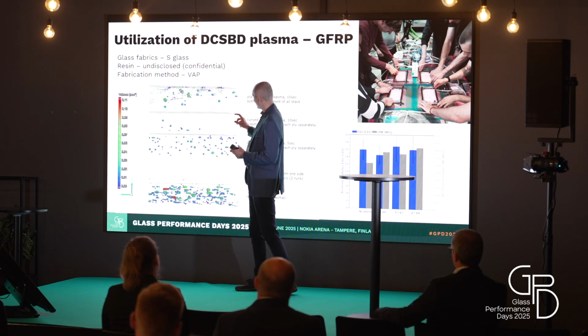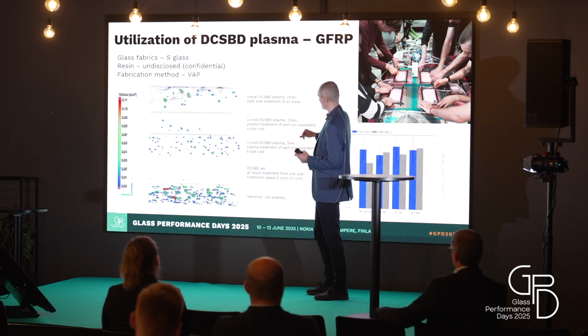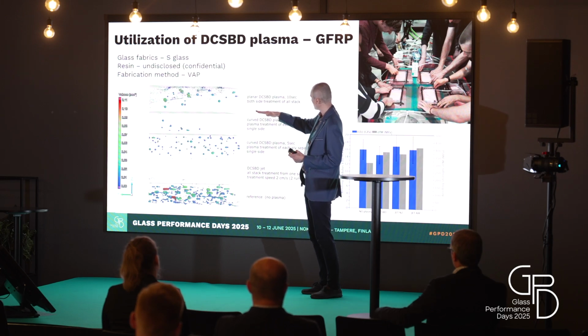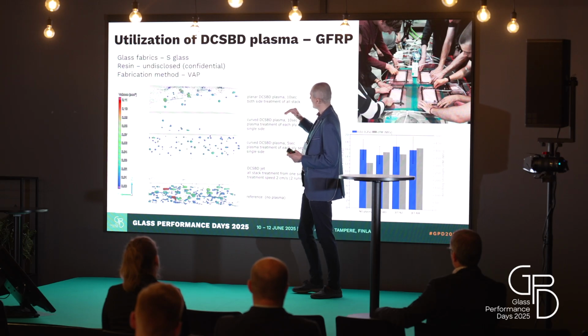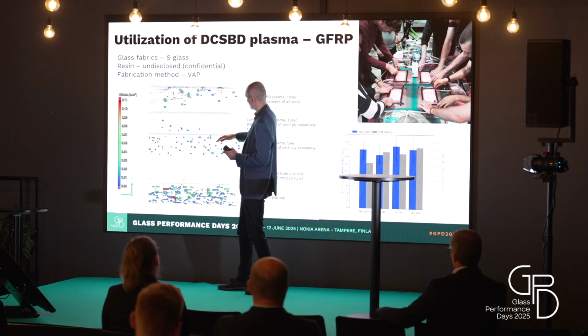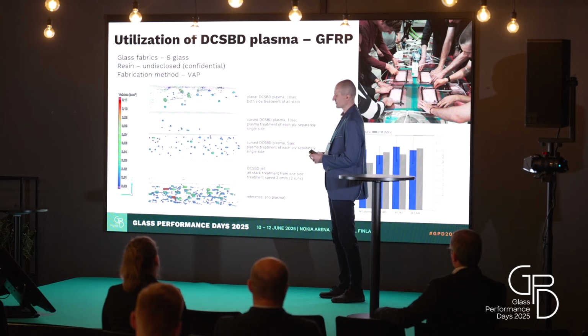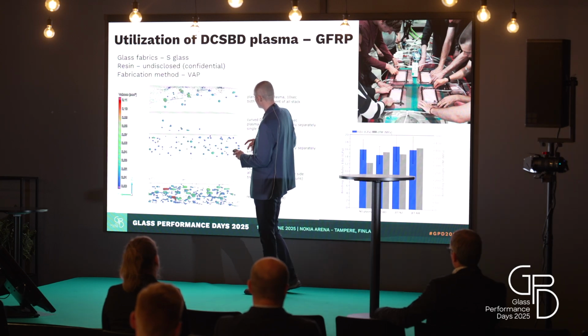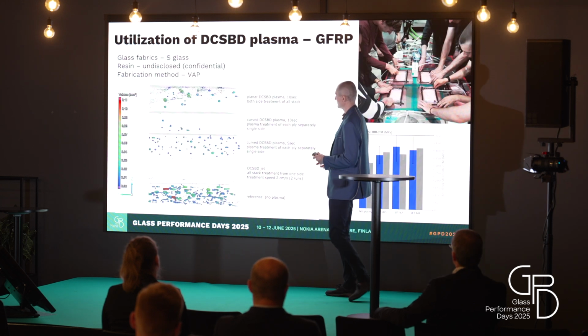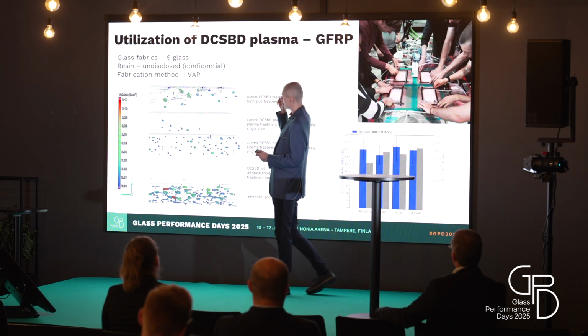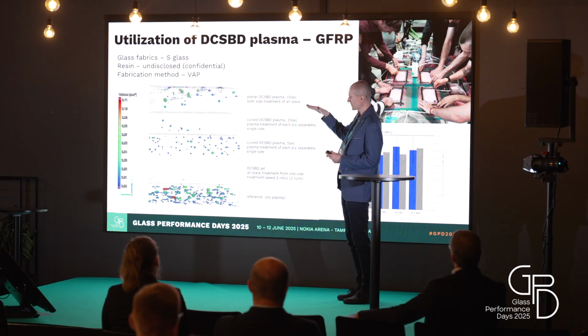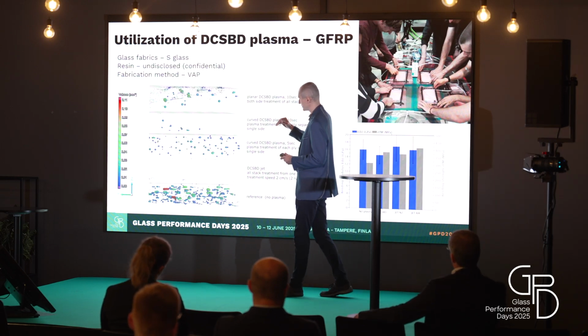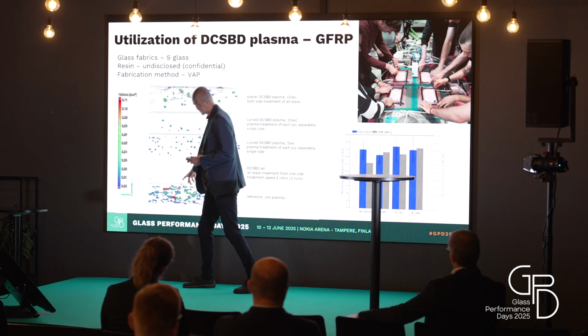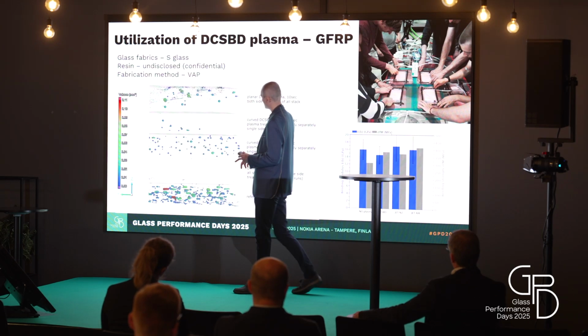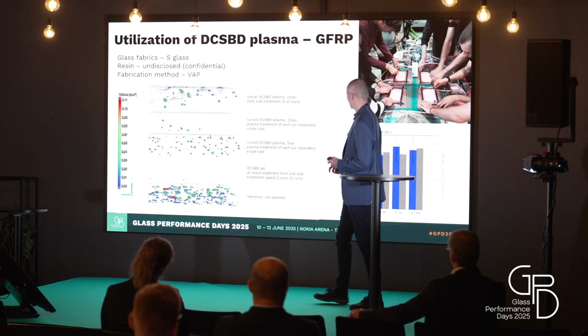And also, there is a significant difference between the plasma applications. When we treated with the surface plasma, when each ply of the glass fabrics was treated, we significantly decreased the number of voids. But using this linear jet plasma system, we were able to treat all the stacks of multiple layers of glass fabrics at once. And as you can see here, there is a nice uniform composite material without any voids in the material.